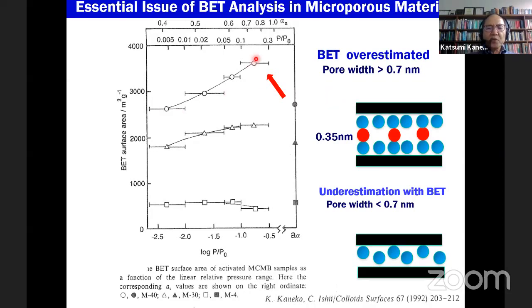Here I will show you one example. This is the surface area plotted using data in different relative pressure ranges. This is the low pressure range, 0.005 to 0.101. But for the standard region, the values are very large, while the exact one is around here. So it is highly overestimated. But if the pore width is less than 0.7 nanometer, no monolayer adsorption occurs on both walls, then underestimation occurs, as shown here. So the evaluation of the surface area of porous carbon should be very careful.